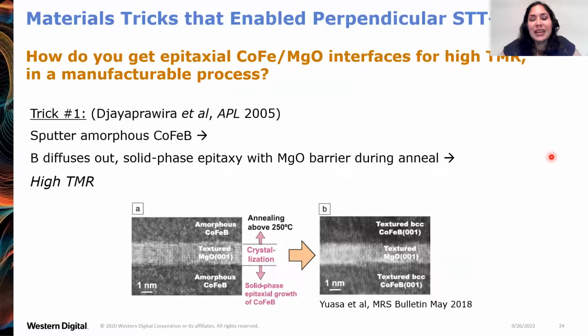So my role in the MRAM research team at Western Digital is to do the sputter deposition and characterization of the MRAM stack. And so I want to share with you a couple of tricks that we use day in and day out to make high quality magnetic tunnel junctions. And this trick here is used in manufacturing of the tunnel junctions that are used in read heads of hard drives too. So this trick addresses the question, how do you get epitaxial cobalt iron MgO interfaces? I had described to you that this interface is critical for high TMR. How do you get that in a manufacturable process?